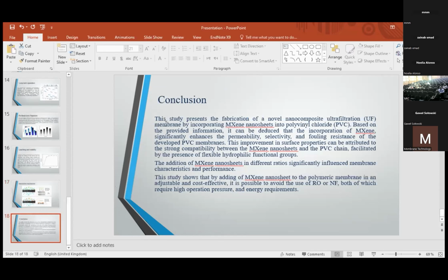In conclusion, this study presents the fabrication of a novel nanocomposite ultrafiltration membrane by incorporating MXene nanosheets into polyvinyl chloride, PVC. Based on the provided information, it can be deduced that the incorporation of MXene significantly enhanced the permeability, selectivity, and fouling resistance of the developed PVC membrane. This improvement in surface properties can be attributed to the strong compatibility between the MXene nanosheet and PVC chain. The addition of MXene nanosheets in different ratios significantly influences the membrane characteristics and performance.